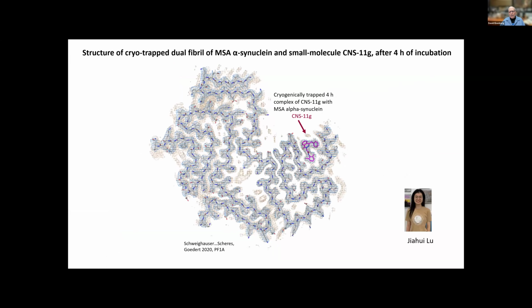So then Jiahui Lu formed, as I showed you with the tau work before, a cryotrapped structure of CNS11G in alpha-synuclein fiber, an MSA alpha-synuclein fiber. And here is the CNS11G. This is one layer. Now we're looking down a fiber of alpha-synuclein, and it's also a fiber of CNS11G. It's a dual fiber. So it's trapped at 4 hours. If she lets it go 24 hours, then almost all the fibers disappear. Actually, it only takes a little over 12 hours, and both fibers disappear.